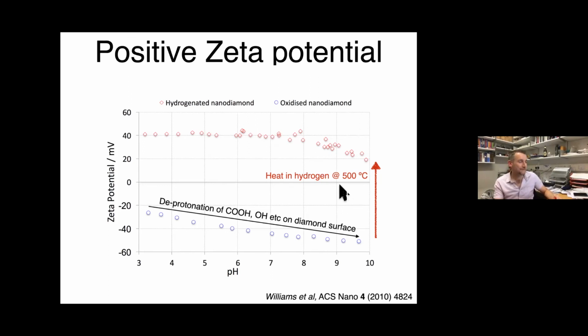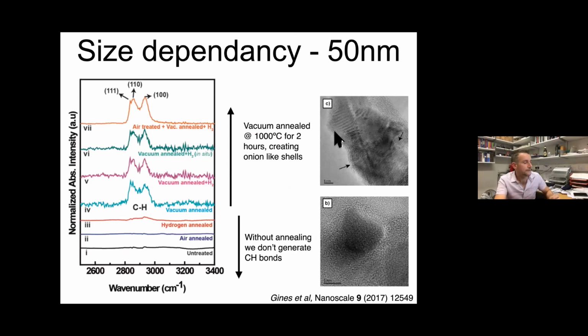Well, a little bit. But at the time, I speculated in this paper that it's something to do with the sp2, because I tried it on bigger particles and it didn't work. That was my hand-wave argument, not a very good one. But more recently in Cardiff, Laia Guinness, who was working for me and is now a PhD student in Uppsala, came up with the idea: why don't we take the particles it doesn't work on and anneal them to create sp2 and see if it works then.